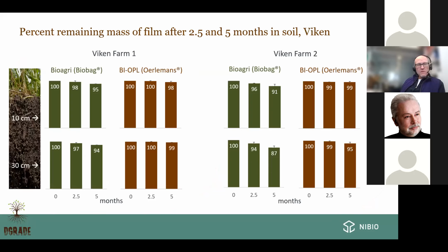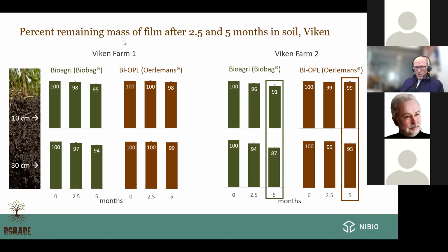When we looked at the degradation, I will only present here the mass loss of the plastic film after 2.5 and 5 months for the different farms and the different types of plastics. As you can see here, the most we could see of degradation was around 9 to 13%. So not enormous during an entire growth season, but the BioBag performed a little bit better than the Erlemans film in most cases.